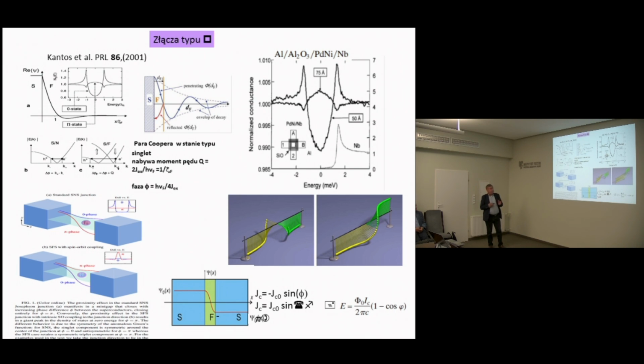Namely, before that, there were many experiments going on where two superconductors were separated by a ferromagnet. And as the thickness of the ferromagnet increased, the TC did not decrease monotonically, but TC showed a minimum and then again increased. And the explanation for that is the so-called Fulde-Ferrell-Larkin-Ovchinnikov state. It means that we have non-zero momentum, and in such a case the real part of the order parameter can be negative, and if it's negative, then we have the so-called pi state. And the density of states for a zero junction looks like that, whereas it is quite opposite for a pi junction.